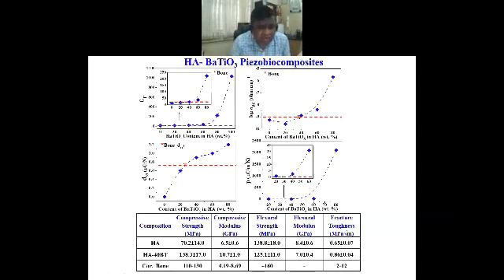And there are many other properties that we have also measured, particularly AC conductivity and so on. Again, bone-like conductivity properties like 10 to the power -9 ohm inverse centimeter inverse, we have got with only around 40% barium titanate addition to hydroxyapatite. So therefore, we have further focused our study.